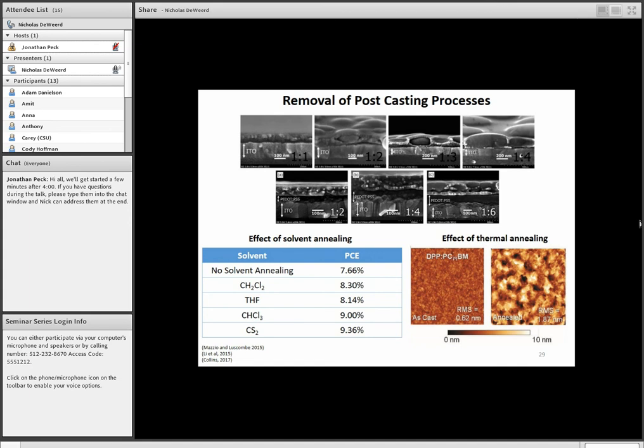And then for thermal annealing, you can see that the device on the left for the thermal annealing, these are AFM images, or atomic force microscopy. And so the figure of merit here is this RMS value. That's the root mean squared. The root mean squared value, basically the larger that value, the rougher the surface in this particular measurement. And on the left, this is a device that has not been thermally annealed, and it's relatively smooth. And then on the right, you see a device that has been annealed.